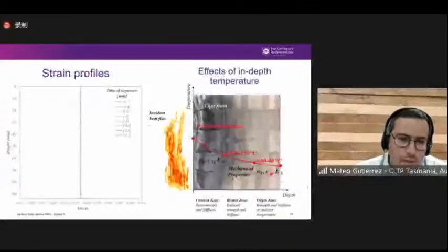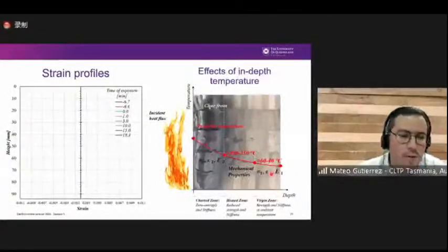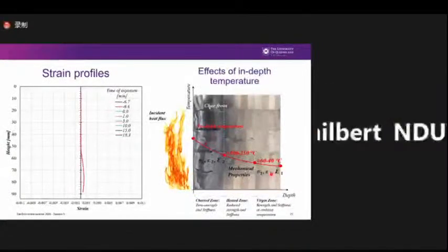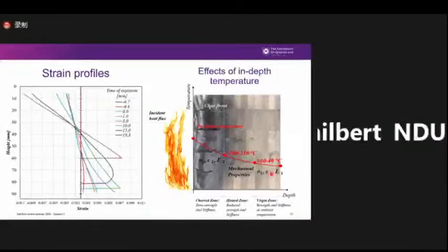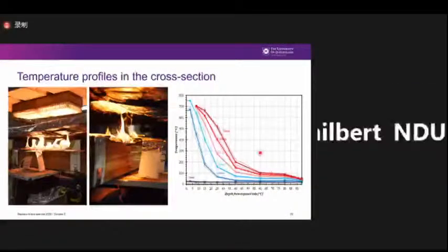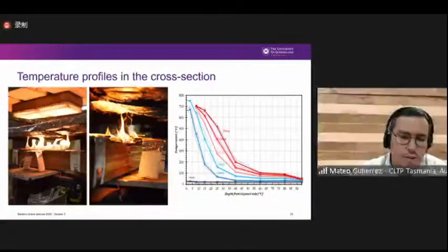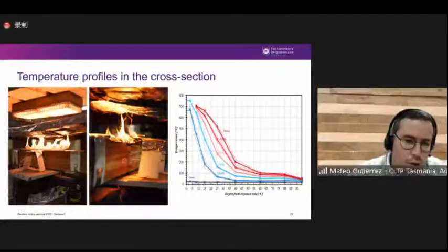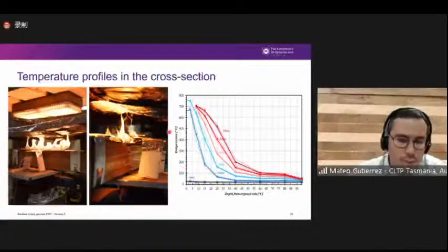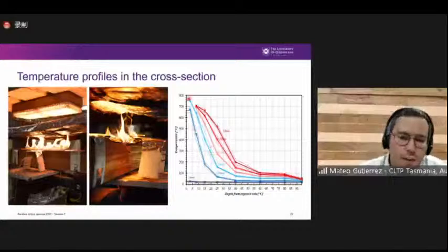So here you will see some results of the strain profiles. So basically you can see the strain profiles at different times, right? Until reaching the failure. And because, as I mentioned before, we created these constitutive models for different temperatures, we needed to know the temperature distribution in the cross section. So in order to do that, we installed thermocouples at different depths. And with those thermocouples, we were able to measure the temperature distribution within the beam. This is something that can be done with a numerical model, but in order to reduce the uncertainties in our structural calculations, we just decided to do this from an experimental setup.